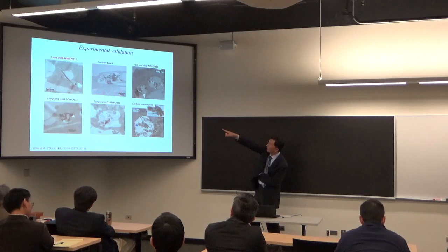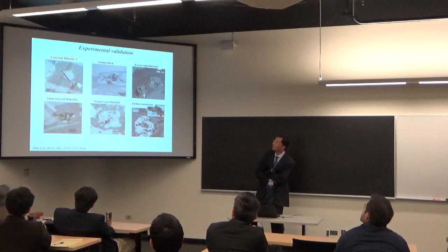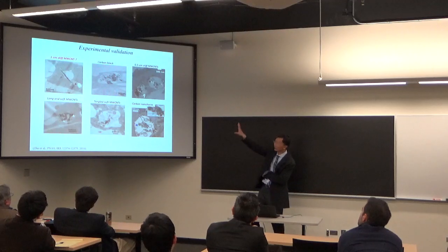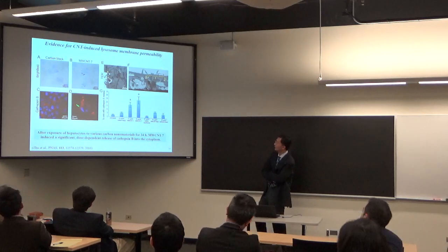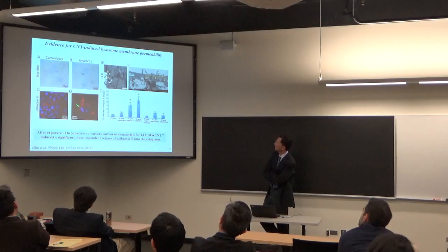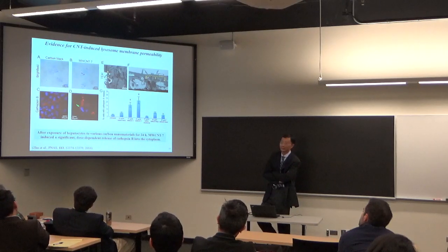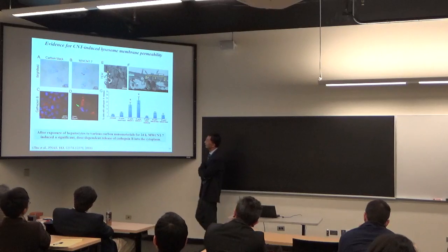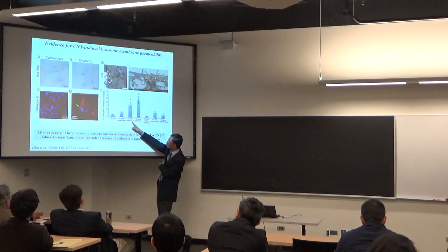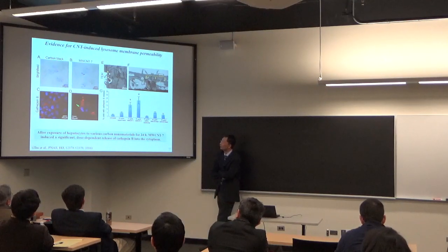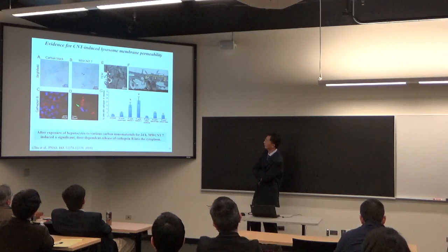So what we found, in the upper left case, the one-micrometer-long stiff carbon nanotube, all these have the same chemistry, only in that case shows toxicity. Here we measure cathepsin B. Cathepsin B is an important enzyme within the lysosome. Release of cathepsin B is known to lead to cell death, apoptosis. We measured cathepsin B release of cells with many different kinds of materials. We find only the stiff multiwall carbon nanotube, one micrometer, shows a dosage-dependent release of cathepsin B. The more nanomaterial you feed, the more release of cathepsin B you have.